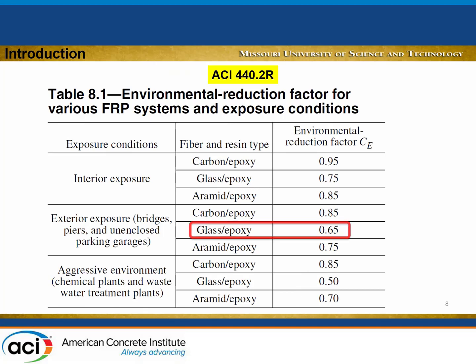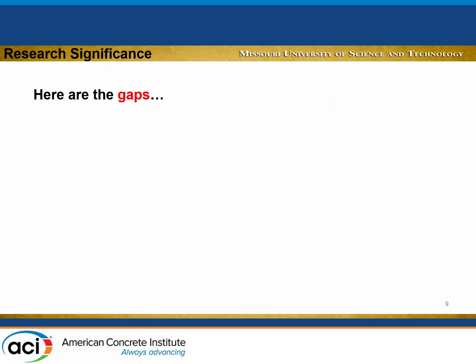And then, as you're probably familiar, right now the ACI 440 has an environmental reduction factor for glass epoxy of 0.65. The gaps that we believe are available in the literature, the first one is the sustained load conditions. Most of the testing on the glass fiber that has been done is either at the material level or without applying sustained load. Sustained load may cause some cracking, micro cracks, and then maybe cause some long-term reduction.